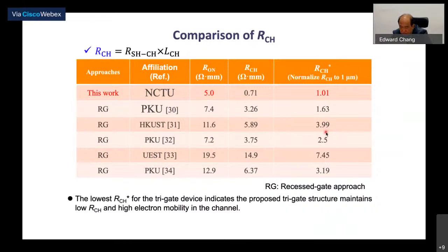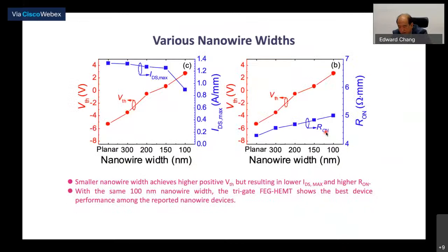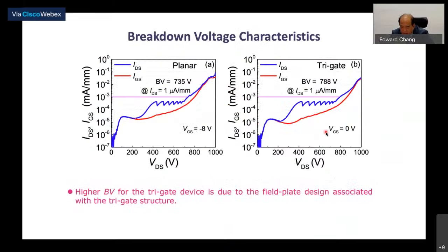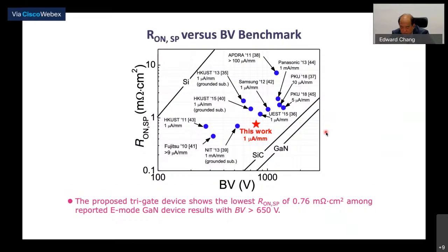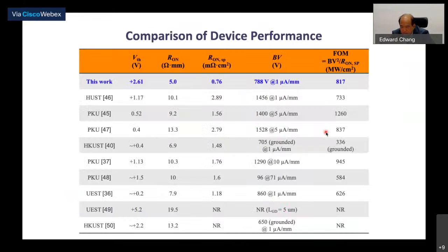We get very low channel resistance, and to do that, as I mentioned, your nanowire must be 100 nanometer or below, so you can turn everything off. The breakdown is also good enough, around 700 to 800 volt. So if you benchmark against other devices, this meets all the characteristics and is by far probably the best performance.